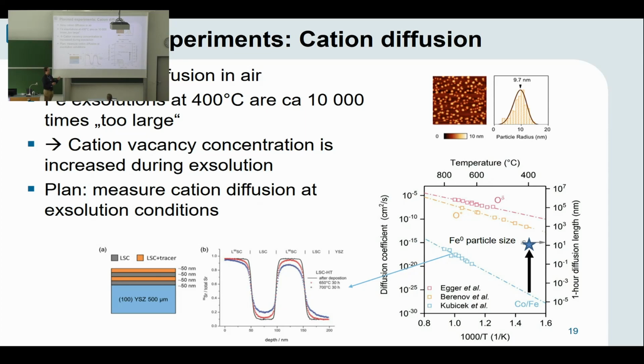Of course, in the exsolution there must be a lot of cation motion, and also the bulk deforms because it's forming a void in which the particle is anchored. But this appears to be very localized to the exsolved particle. So you'd see something going down, then the particle sitting in a ditch or a depression, or a void. With the very small particles, it's hard to observe. But the model is that first a well is forming, and then the particle is exsolving into the well, and once the particle sits there, it's basically just filling the well. But I have to admit that this depends very much on the material and exsolution conditions, because you have very many parameters to tune. So there is probably not one single simple answer in all cases.